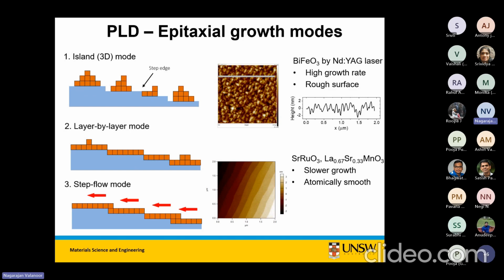Just to go through this very quickly, in one of our chambers, one of our collaborators in France grows the same bismuth ferrite target, same materials, almost the same substrate, etc. Just based on how the growth rate is, we can obviously control how the surface is. So if it's a very high flux, this is in Manuel's lab, if we do bismuth ferrite with the neodymium YAG laser, we get a rough surface, and we've shown that that sample has a lot of internal strain gradients. So the flexoelectricity in that sample is quite high.